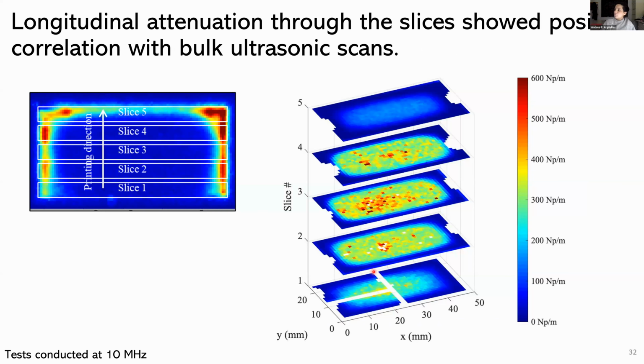So we just assumed that that would be what dominated the response that we were seeing in these samples. When we look at the attenuation results, they supported that. So we cut up the samples. You see that the sample in the middle has higher attenuation. The ones at the edges have lower attenuation. Makes sense. That's all in line with the fact that we're getting low and high transmission in those areas respectively.